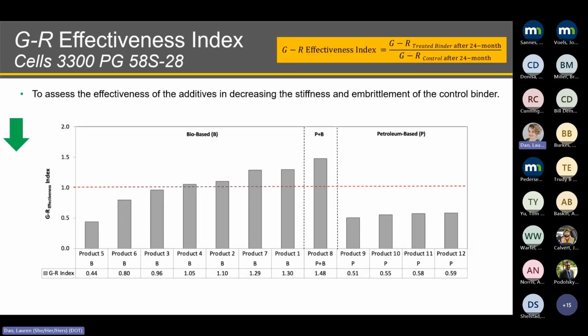Another way that we tried to evaluate if these products are effective or not in decreasing the stiffness and embrittlement of the base binder was using the Glover-Rowe parameter. For this, we created a Glover-Rowe effectiveness index, where we use the Glover-Rowe parameter of the treated binder from field cores collected after 24 months of field aging, and divide it by the calculated Glover-Rowe parameter of the control binder also after 24 months of field aging.